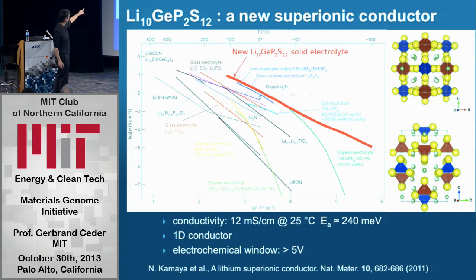But here's the good news. The conductivity is the red line. This is a 1/T plot. The activation energy is much lower. So if you go to low temperature, this stuff is actually even better than a liquid electrolyte, and batteries sometimes have issues at low temperature. So this is an amazing material.